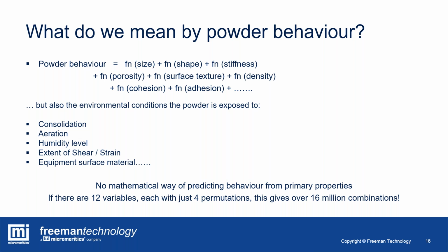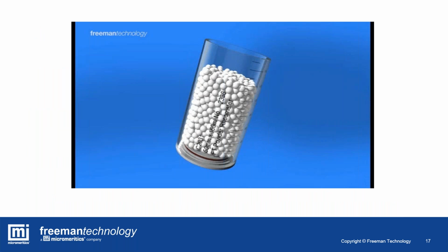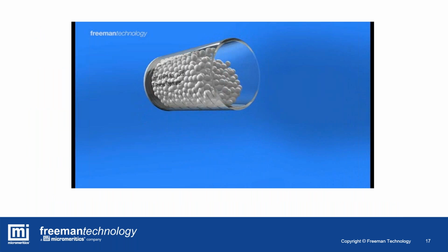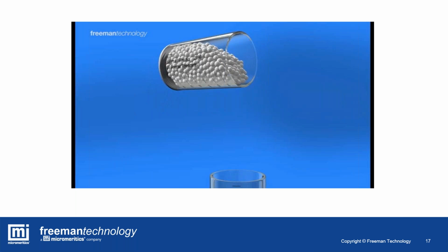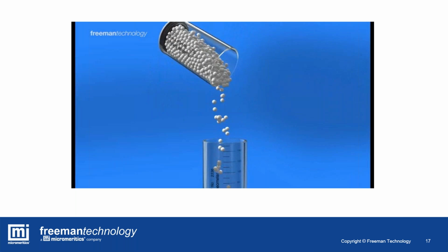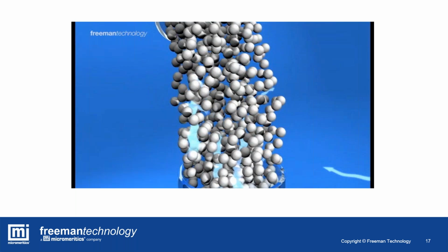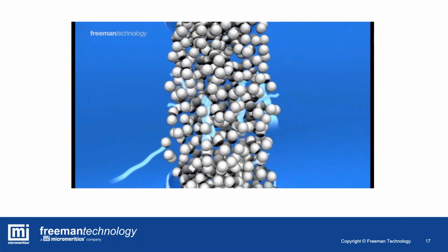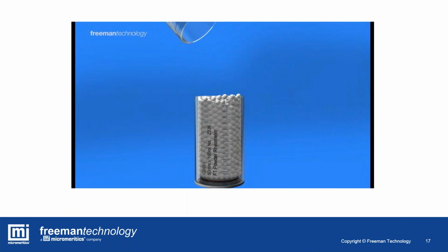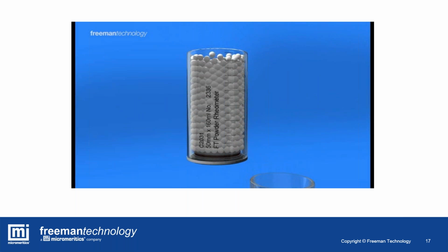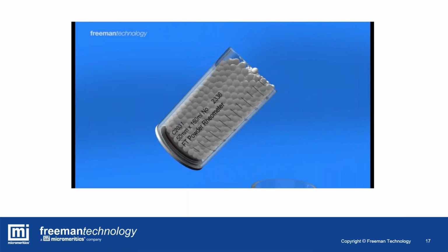And you can see in this animation an illustration really of how these particles interact and behave under different stress conditions. If you discharge a powder under gravity, the powder bed will naturally dilate and air gets into the bed. The density reduces, and actually the flowability, the ease with which it discharges the second time, is much easier. It becomes much more liquid.